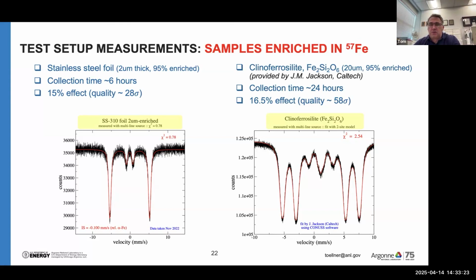You see the percent effect and the quality. Again, this is the level that you get for enriched samples. In 24 hours, this would be the level you would get in 24 minutes with a new source, assuming it's a 3 gamma line width.